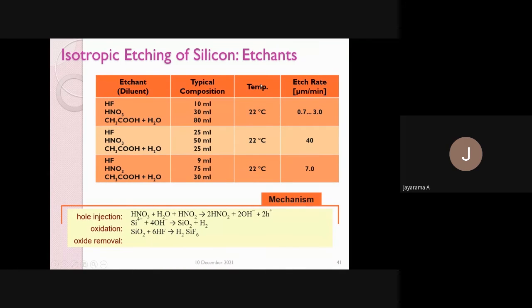See this, all these are etched at 22 degrees Celsius, with 10 ml composition, 30 ml composition, 80 ml composition. The range is 0.7 to 3 micrometer per minute.